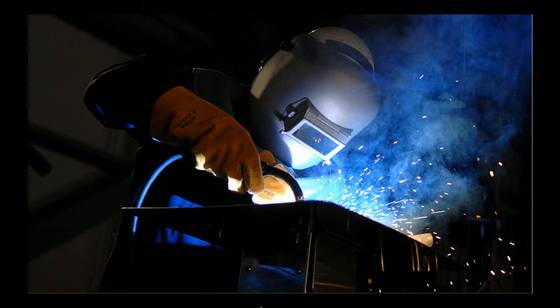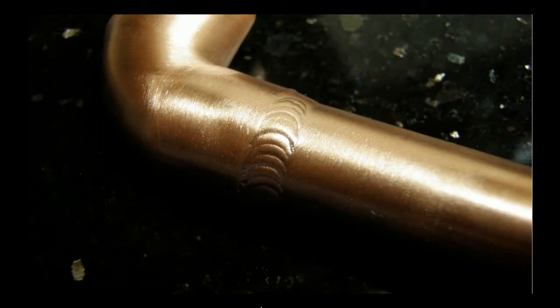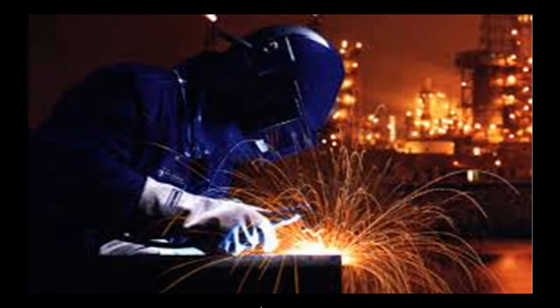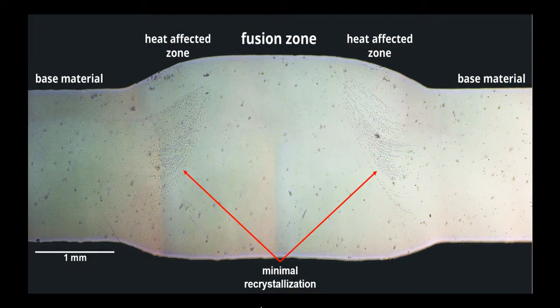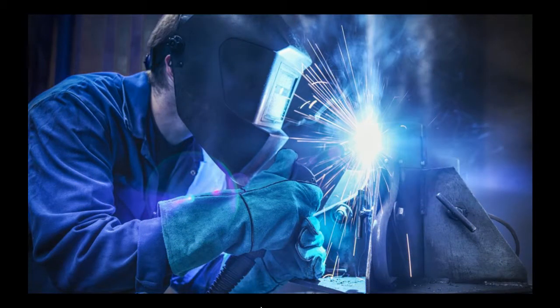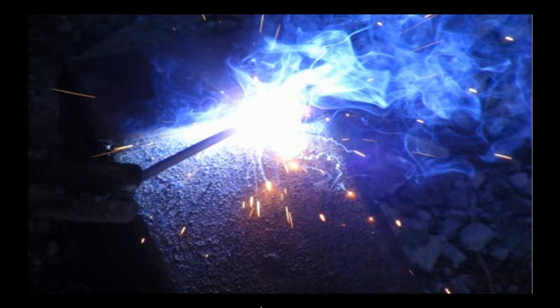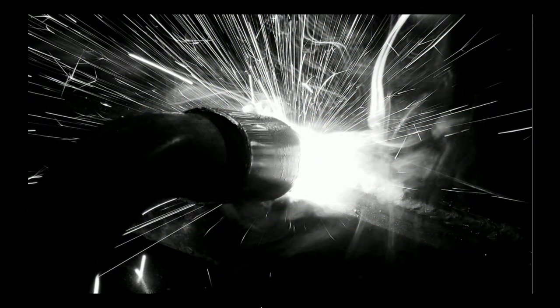Cast iron melts at approximately 2300 degrees Fahrenheit. This is the heat required for fusion welding. It can be joined at 1300 to 1600 degrees Fahrenheit if the low heat input method is used. During the joining operation, the cast iron at the surface of the joint is changed temporarily to steel. Carbon is removed. The special cast iron filler metal alloys readily to this surface, and the joint is completed hundreds of degrees below the melting point of the cast iron.